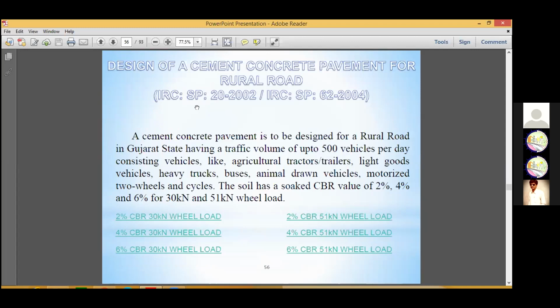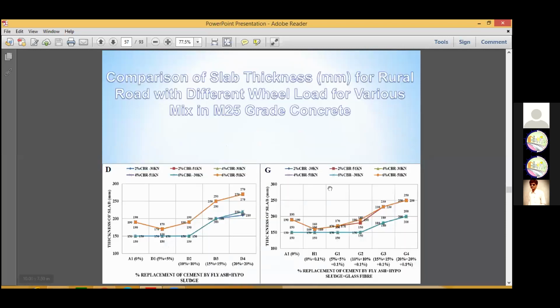Based on IRC SP 20/2002 and IRC SP 62/2004, we have gone for 2% CBR with 30 kilonewton wheel load, 4% CBR with 30 kilonewton wheel load, and 6% CBR with 30 kilonewton wheel load. In the same way, wheel loads of 30 kilonewton and 51 kilonewton. So with 2%, 4%, 6% CBR and the different wheel loads we have calculated, with 500 vehicles per day, CVPD, for the rural road design. Now with the different wheel loads, the M25 grade as per IRC SP 62/2004, we have designed the concrete for M25 grade, and we refer to the slab thickness of the rural road rigid pavement, which varies from 150 to 270 mm with the different wheel loads, 30 kilonewton and 51 kilonewton.